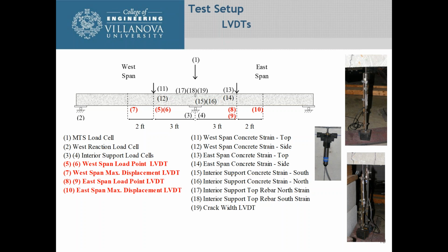So what we did is we put 2 LVDTs at the points where the loads were applied, and one of them was a much coarser deflection. It measured the deflections much coarser. It wasn't as refined as the other one. And so what we did is during the initial deflections, we were using the more coarse one to see when we were getting deflections, and then we would pull that one out in case we got a sudden failure. We also had blocking to make sure that if we did get a sudden failure, we didn't damage any of the equipment.